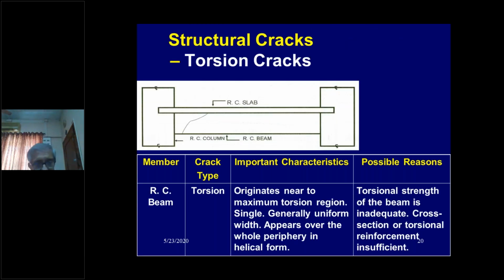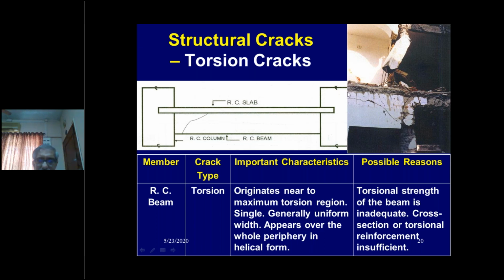The torsional cracks occur near the point where there is maximum torsion region. Generally a uniform width appears and the crack runs over the periphery in a helical form. Torsional strength of the beam is inadequate, cross section or torsional reinforcement insufficient. You can see here, this is the torsional crack. Of course, this is a building in Turkey, which failed. And of course, the column on the top has gone for a toss. But a torsional crack is visible on the beam below, which is helical. And you can see it from the other side also, if you want to go there and risk your life.